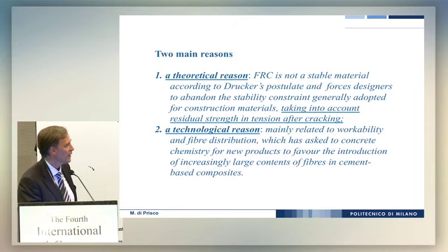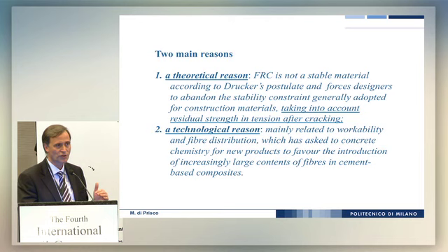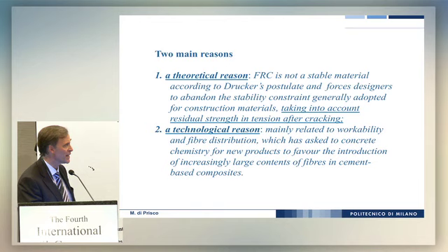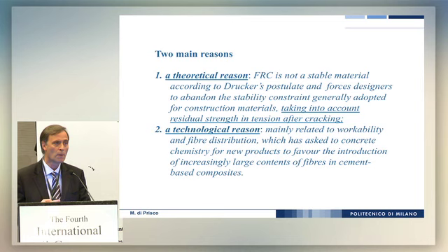The second one is a technological reason, because for a long time there was a sort of limitation in terms of fiber amount inside the mix. And so we couldn't significantly substitute the reinforcement with fibers. But now we have a lot of additives that allow us to pump 100 kilograms of fibers, for instance, per cubic meter. And so this means that the technology is ready.